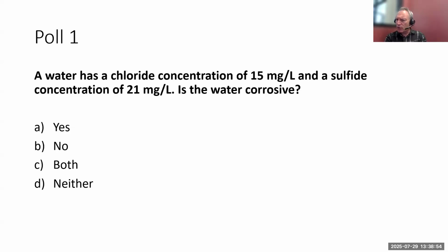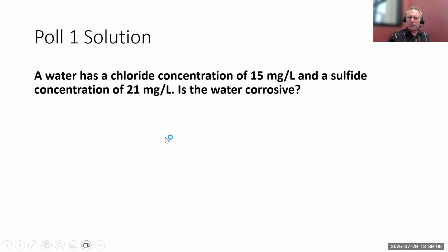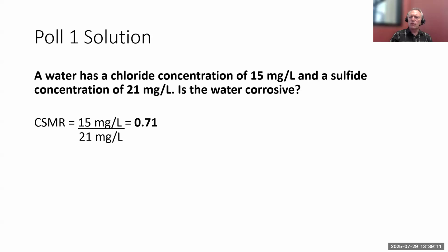And I see most of you, 87% or so, are saying yes, this water is corrosive. And let's look at the solution here. Our CSMR is 15 milligrams per liter of chloride divided by 21 milligrams per liter of sulfide, and that gives us a CSMR of 0.71. It's greater than 0.5, so you are correct that this water is likely to be corrosive.